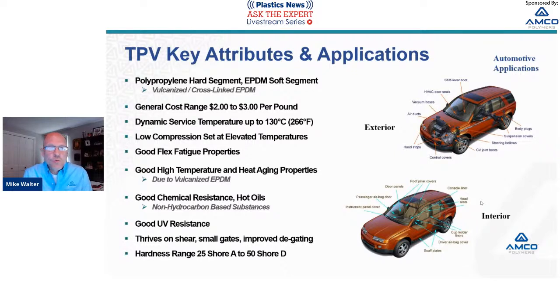The general cost range is $2 to $3 a pound. Dynamic service temperature is up to about 130 degrees C or 266 F. That's the value of the cross-linked EPDM rubber, that high heat capability. In addition to that, you get low compression set values at elevated temperatures. You get good flex fatigue properties at a wide range of temperatures, and overall good heat aging properties.